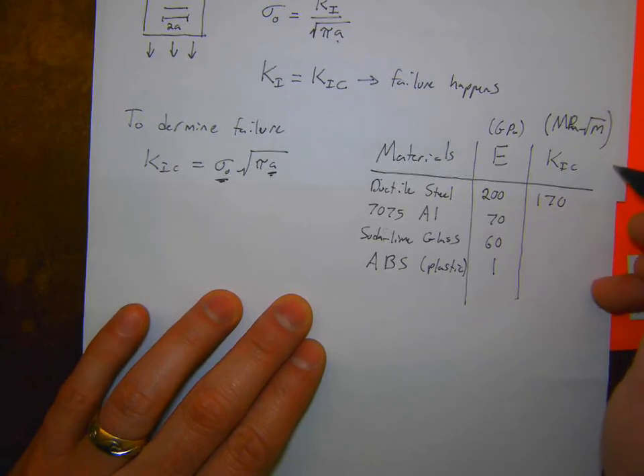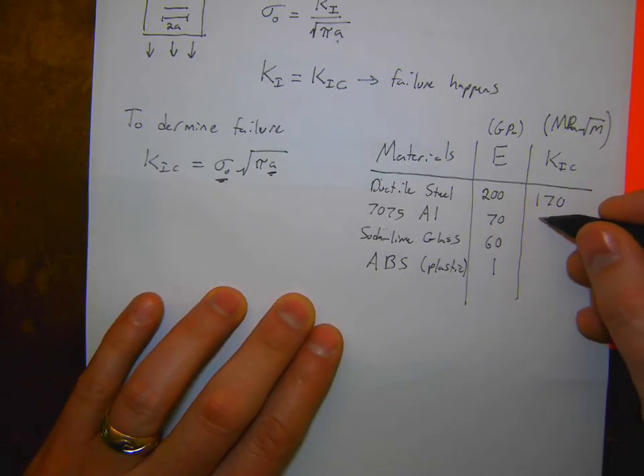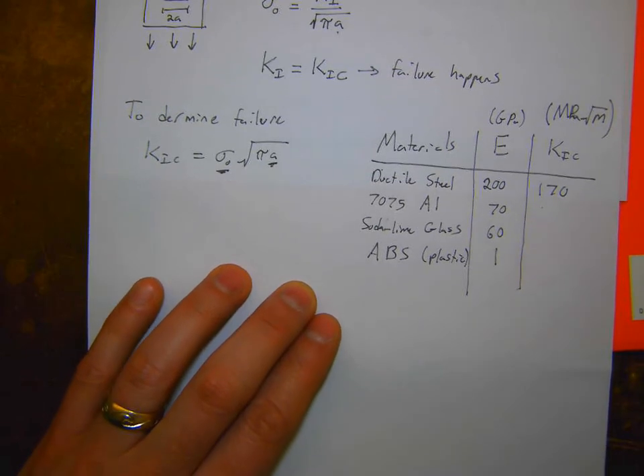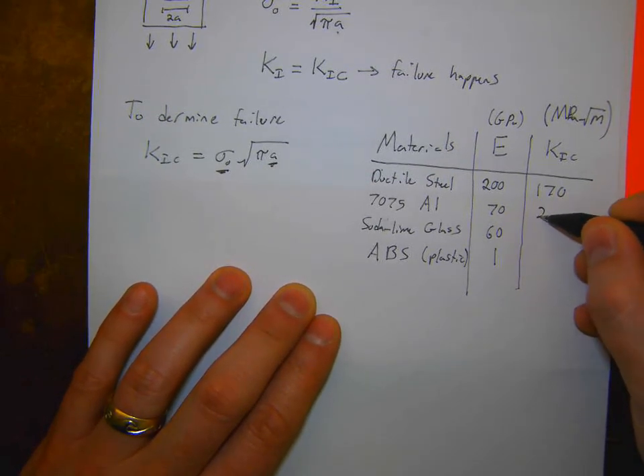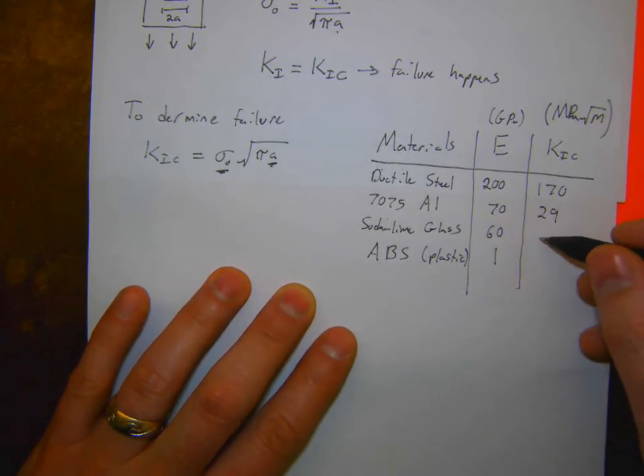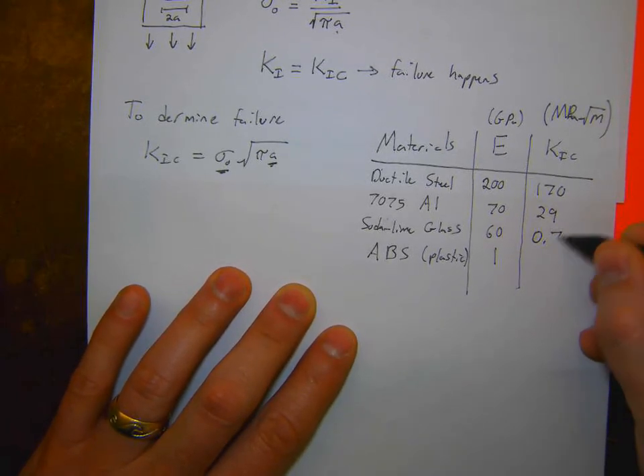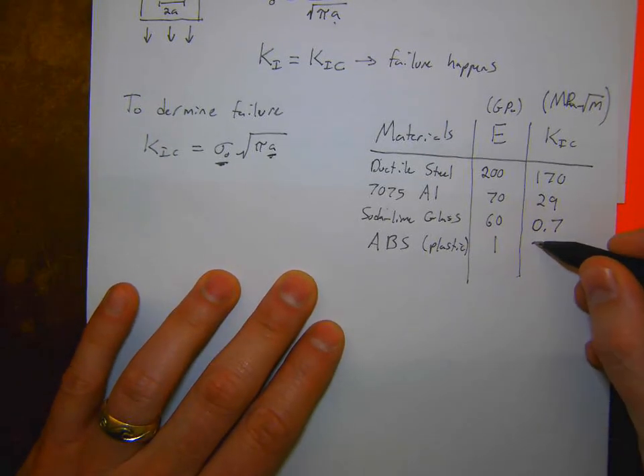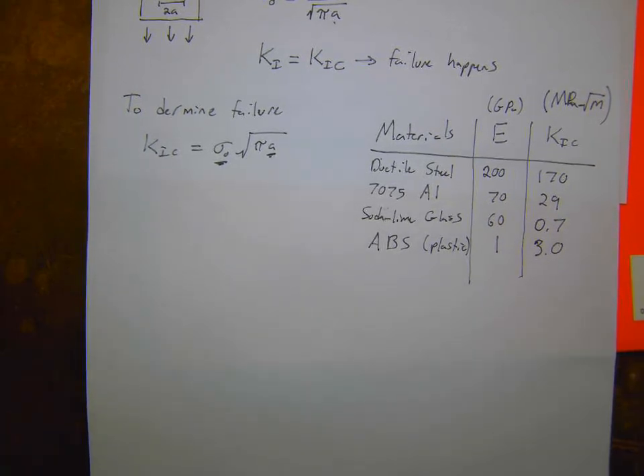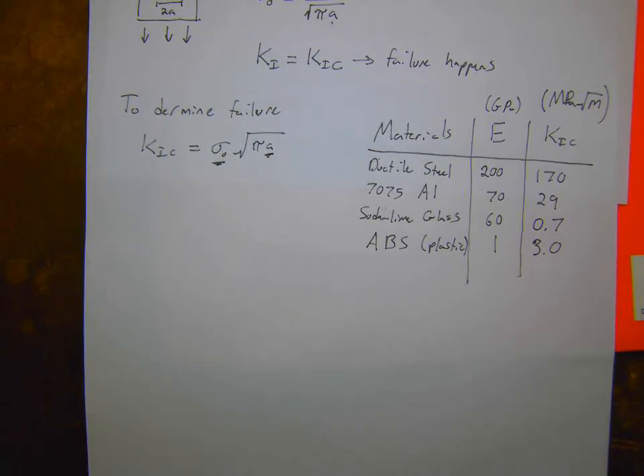So stress times square root of meter. The aluminum, 7075 aluminum, which is a high strength aerospace grade aluminum, is something more like 29 MPa root meters. Soda lime glass is very brittle, so it's something like 0.7. And ABS, even though it has a way lower stiffness, still absorbs a lot of deformation. ABS is what plumbing materials are made out of. It's the stuff that most of your sewage pipes or drainage pipes are made of. Even though it's a lower stiffness, it can deform a lot and absorb a lot of energy. And that helps it to have a higher toughness.